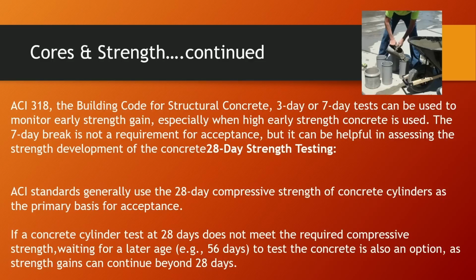ACI standards generally use the 28-day compressive strength of concrete cylinders as the primary basis for acceptance. So you are going to keep having those cylinders broke until you meet that strength. If a concrete cylinder test at 28 days does not meet the required compressive strength, waiting for a later age, i.e. 56 days, to test the concrete is also an option, as strength gains can continue beyond the 28 days.